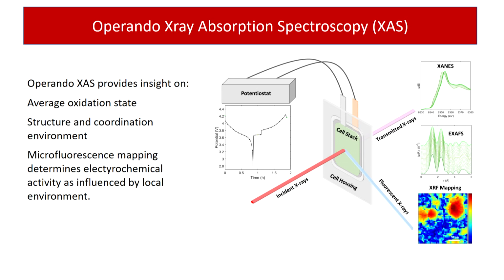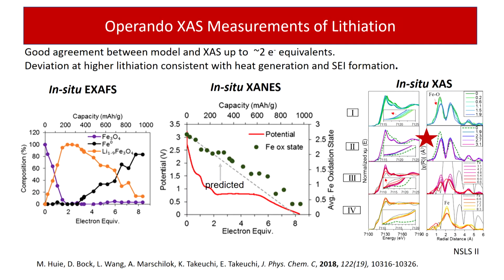And we can also do mapping, where we find not only where the active particles are, but can then interrogate the particles and aggregates for their oxidation state on a local level. This methodology was extraordinarily useful in gaining insight into the calorimetry results. We conducted in situ, actually operando XANES and XRF for a discharging and charging battery.